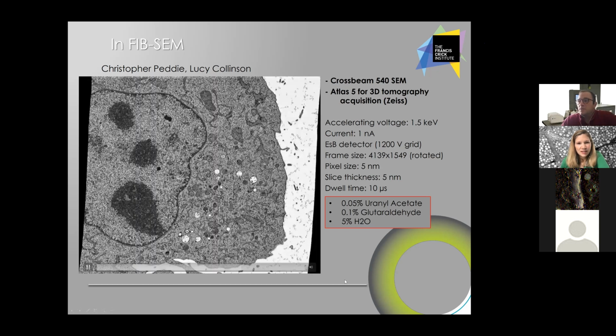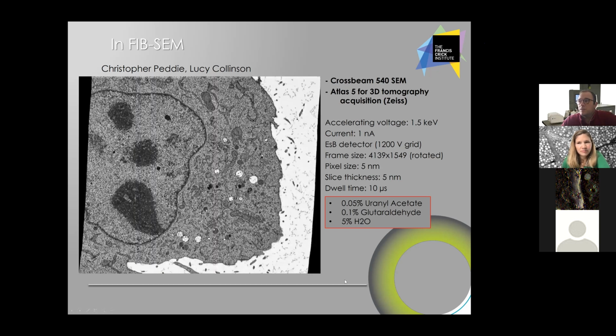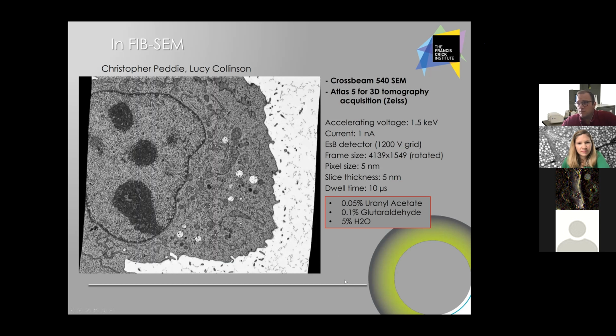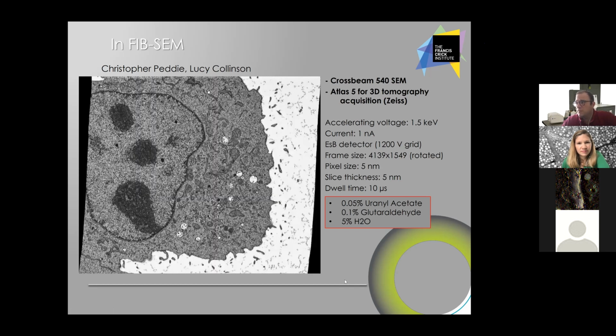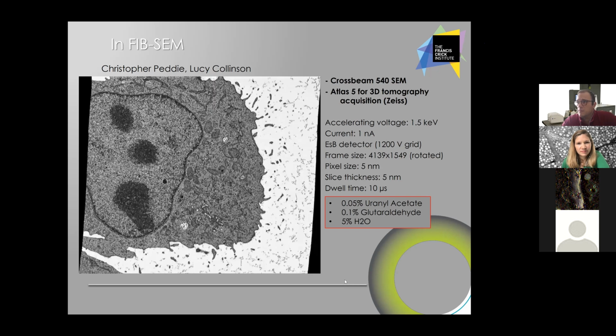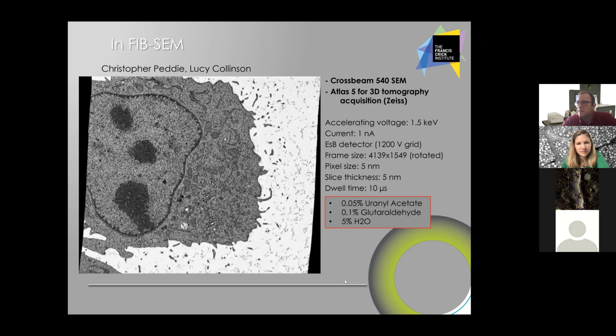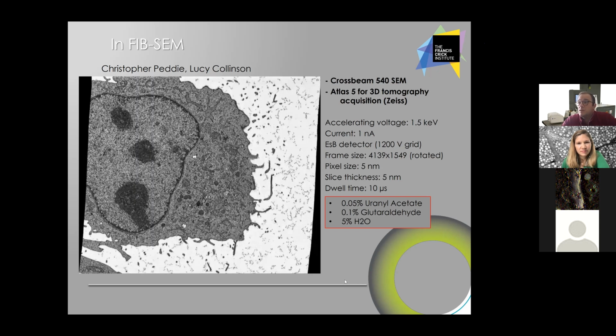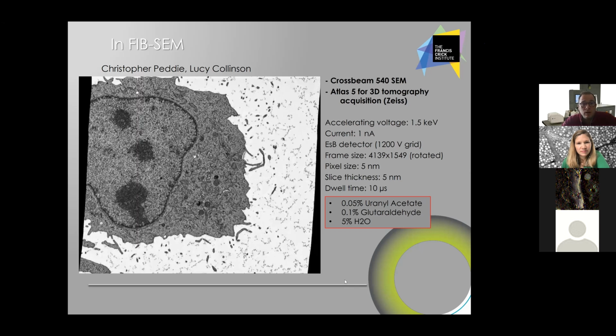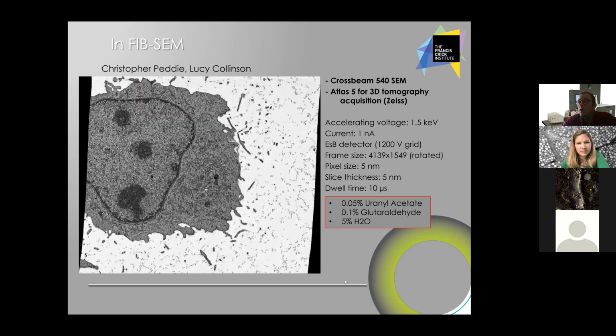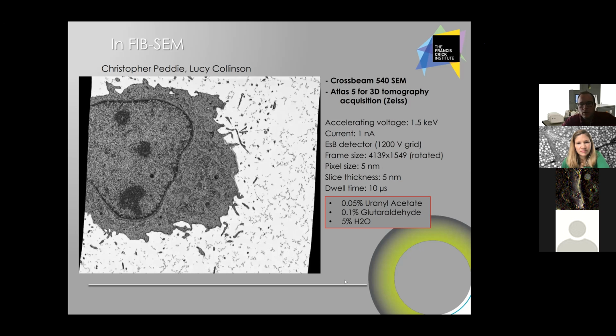And so, as you can see, in FIB-SEM, we could acquire the entire volume. The jumping is coming from the presentation. Obviously, in this case it is not coming from the imaging or from the data set. And as you can see, we can go through an entire cell with a very high contrast and no obvious charging appearing during the imaging.